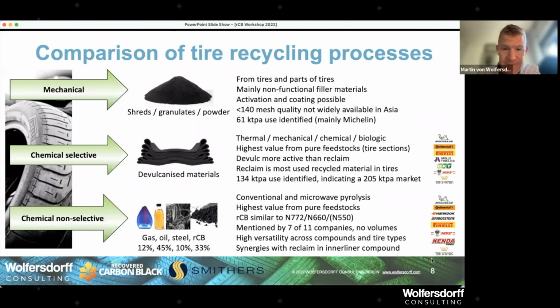Recovered carbon black, just broadly, is in rubber very similar to soft blacks. And the soft blacks are N772, N660, and N550 groups. So carbon black, I have a slide on carbon black, to explain what carbon black is and how carbon blacks are categorized. But these are called semi-reinforcing carbon blacks. And recovered carbon black is in the rubber performance similar to semi-reinforcing carbon blacks.